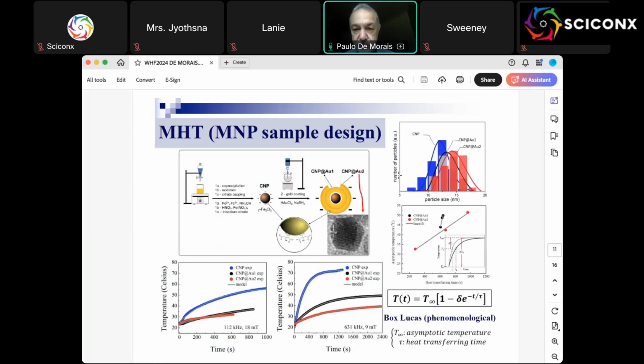In terms of particle size distribution, you can see here on the right-hand side, the upper plot shows the particle size distribution. The blue histogram is the naked maghemite nanoparticles. Then with the first coating, the thinner gold layer on top of maghemite, you can see the gray particle size distribution here, and you can see that the mean size slightly shifts to higher values. And when we coat with a thicker layer of gold, we see the red curve, which is shifted to an even higher mean particle size. So we can modulate the thickness of the gold layer on top of maghemite nanoparticles. Besides, of course, we can modulate the mean size of the core magnetic nanoparticle.